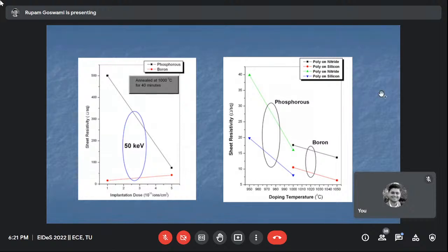Here in the second slide, you can see that this is not implantation. This is thermal diffusion. By thermal diffusion, you can see the effect here because of the temperature. In both cases, phosphorus and boron, the variation is that of poly on silicon and poly on nitride.